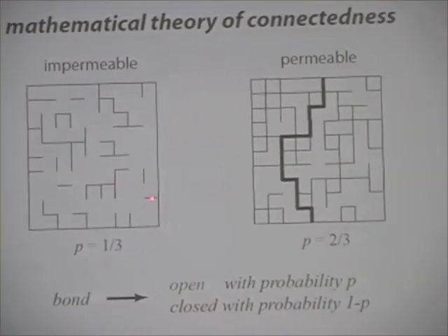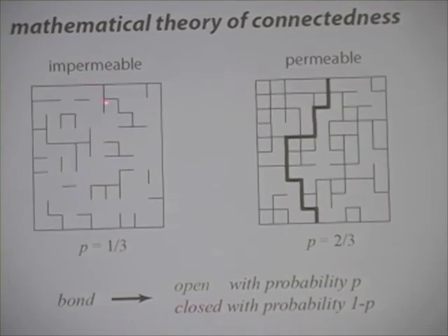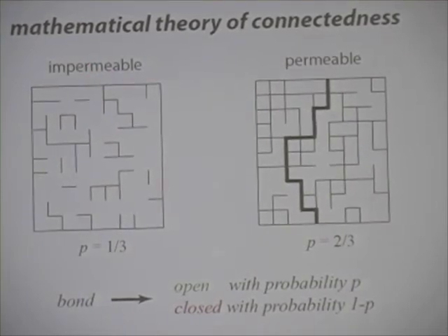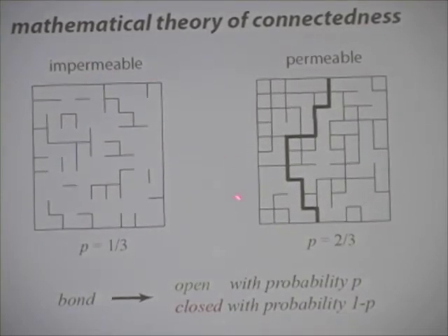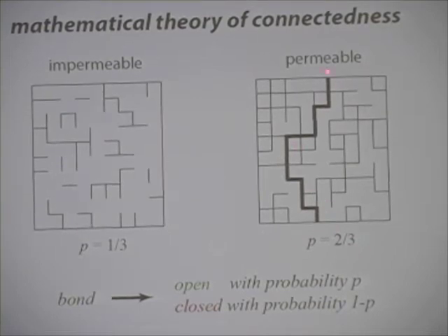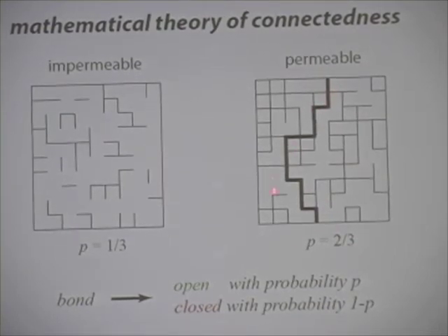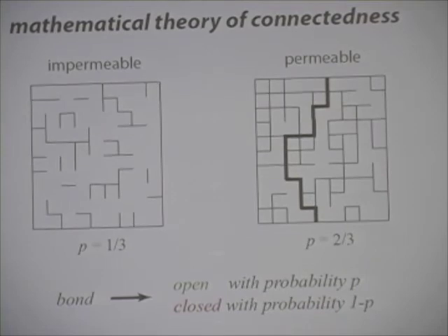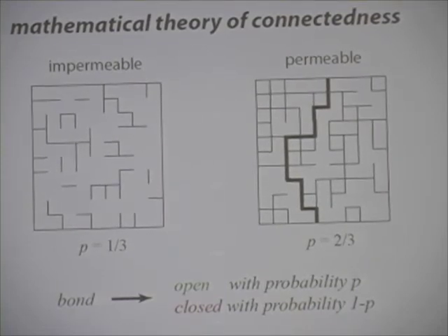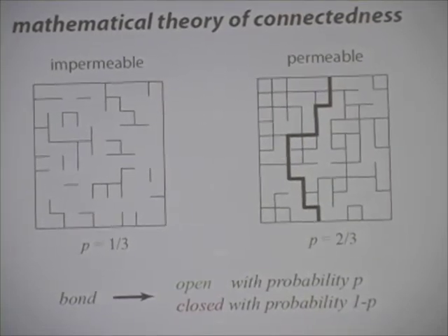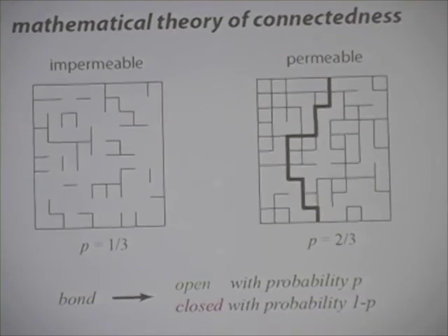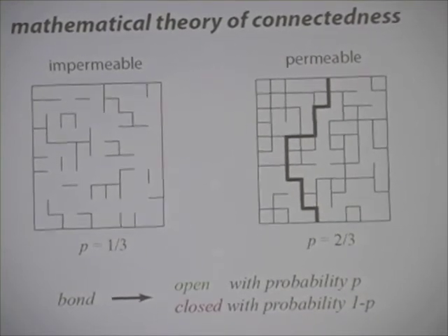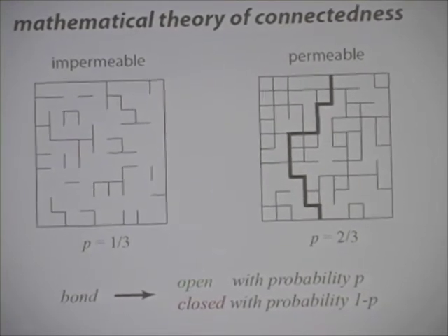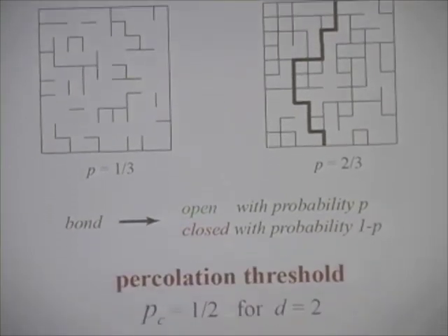So when P is about a third, you see these clusters here, but there are no connected pathways. So fluid can't drain through there, or electricity can't flow. But now at P equal 2/3, this is a permeable state. There's a connected pathway. And it turns out that the critical threshold, the smallest P for which, if we are in an infinite lattice, we have an infinite connected cluster, turns out to be exactly 1/2. And we might call this a tipping point for connectivity.